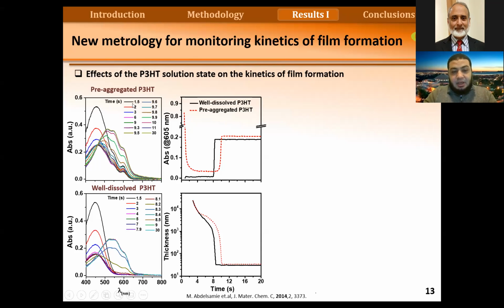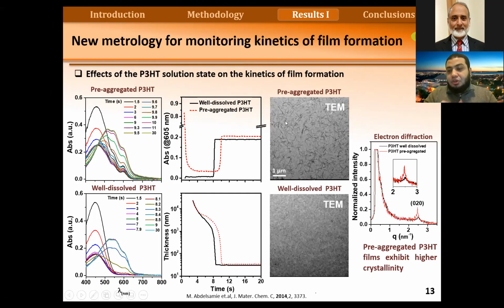And as we can see here at the beginning of spin coating, we can see these peaks from the absorption. They are vibronic peaks, and this is related to the aggregation of P3HT in solution. We can see these clearly in the initial state. And during spin coating, we can see differences in the dynamics. We can have a longer time for the formation with the pre-aggregated solution, and this results in a large effect on the final state.